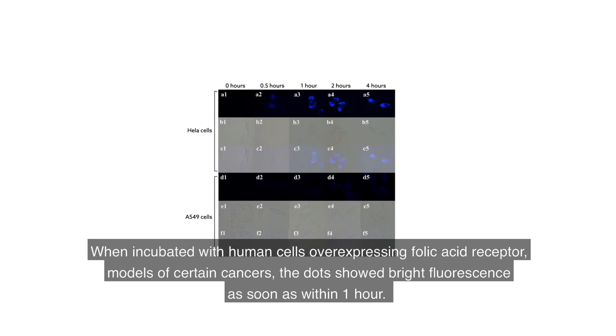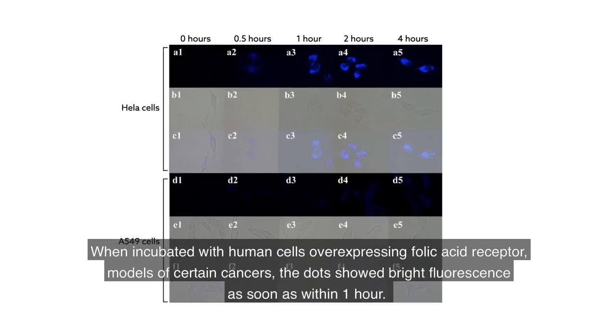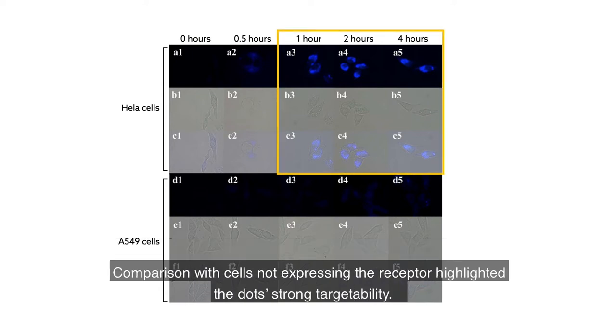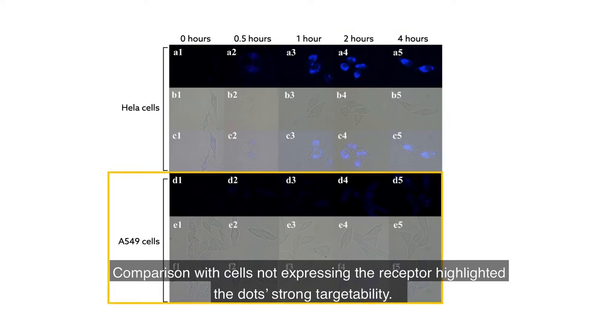When incubated with human cells overexpressing folic acid receptor, models of certain cancers, the dots showed bright fluorescence as soon as within 1 hour. Comparison with cells not expressing the receptor highlighted the dots' strong targetability.